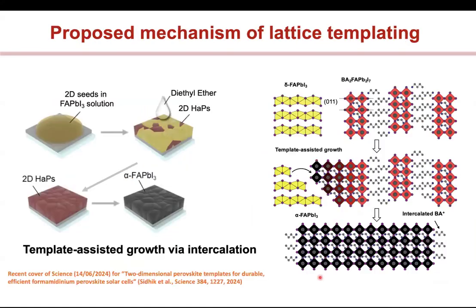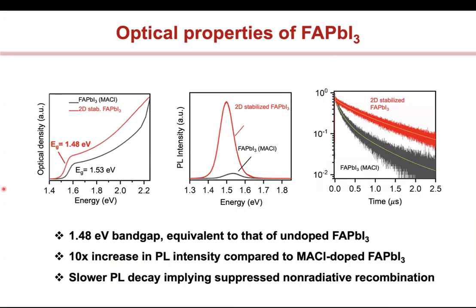And I'll skip this, but in fact, the mechanism is what I said, is that you have this butyl ammonium, the 2D perovskite, and so this FAPI finds a surface where it can nucleate and starts to grow on that surface, and eventually you get this type of 3D perovskite, which is now nucleated on these templates or the seeds of the 2D perovskites that we have added in here. And in fact, you can get these beautiful optical properties.